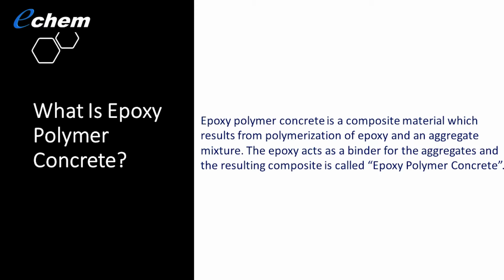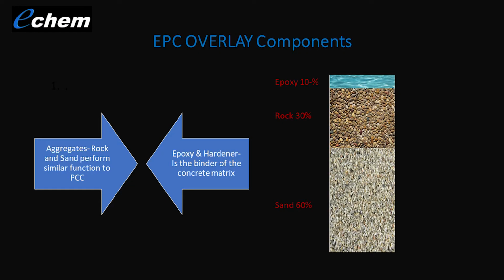So what is epoxy polymer concrete? Epoxy polymer concrete is very similar in use to traditional Portland cement concretes. We take aggregate, we take sand, and we use epoxy polymers as a binder. Kind of the secret to the sauce here, we need to keep the resin loading very low for our EPC concrete. We target 10.5% to 12% by weight. So it kind of works out in this matrix: 10% epoxy, 30% coarse aggregates, and 60% sand. Very similar to a Portland cement mixture.